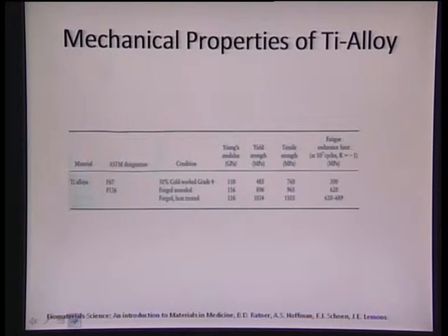But one thing that is seen is that for titanium alloys, the Young's modulus doesn't change much even with certain additions. For commercially pure titanium, which is cold worked to around 30%, we see a yield strength of around 485, tensile strength of around 760 MPa, and a fatigue endurance limit of around 300. But as soon as we start adding alloying elements, like in the case of titanium 6 aluminum 4 vanadium, and that material is forged, annealed, and heat treated, we can see once it is annealed an increase in the yield strength up to around 900 megapascals, tensile strength of around 1000 MPa, and fatigue strength is almost doubled, at 10 to the power 7 cycles.